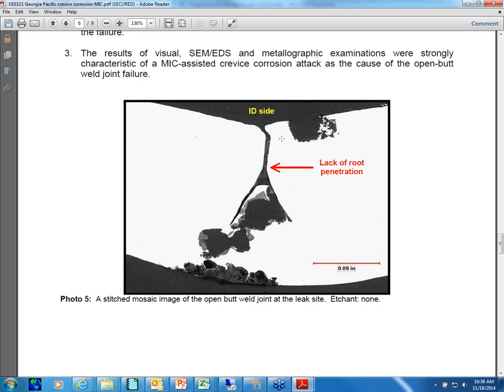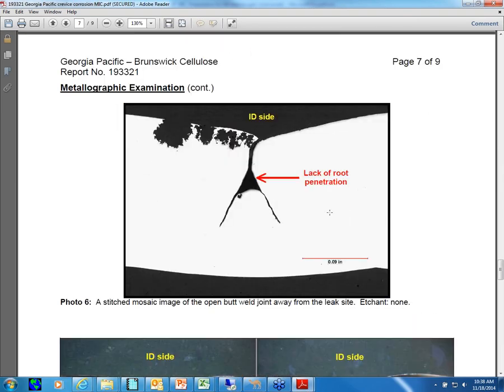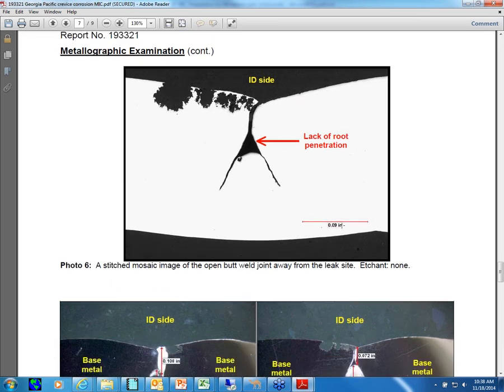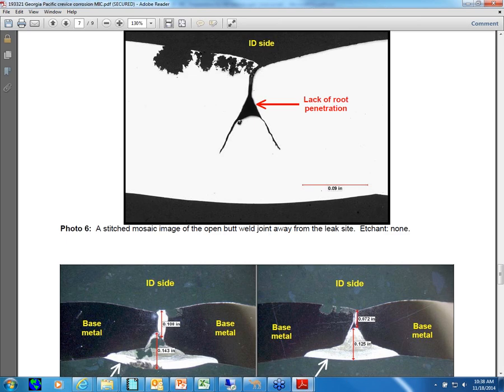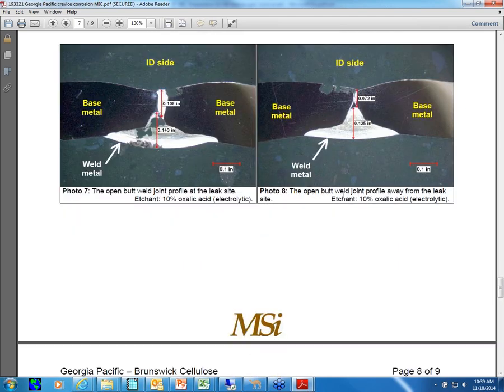For those of you not really familiar with the weld, this would be a butt weld here, one piece here and one piece here. You lay a root in here, and then you build the weld out to the surface of the piping system. So this will be the inside diameter of the pipe, and this will be the outside diameter of the pipe. What you see here is where the metals did not fuse together. They form a little crevice to form crevice corrosion. So this company came back and said, oh, you've got crevice corrosion, just because they found poor welding. Even though poor welding was true, this crevice corrosion over here didn't cause the pitting over here. We actually still had microbes growing on the inside of the piping surface.